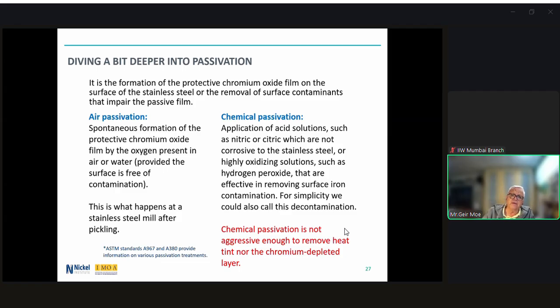But then we can talk about chemical passivation, which is the application of acid solutions such as nitric or citric acid, which are not corrosive to the stainless steel, or it could even be other highly oxidizing solutions such as hydrogen peroxide. All of these are effective in removing surface iron contamination. And in essence, for simplicity, we could also call this a decontamination process. We have to remember chemical passivation is not aggressive enough to remove heat tint nor the chromium depleted layer.